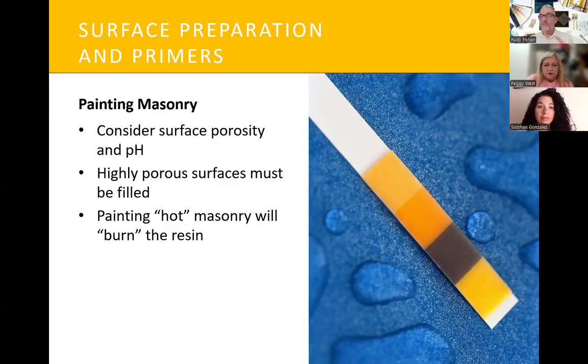And if the resin is the glue of the paint, guess what happens? It starts to powder up the paint. A lot of times you'll see this in new construction where you'll see a nice color, and then you'll see these white areas or white spots occurring. That's where the alkali in the concrete has burned the paint to cause that chalk. Because if you take away the resin from the pigment, what you're going to get is pigment like talcum powder. That's what you're seeing there.